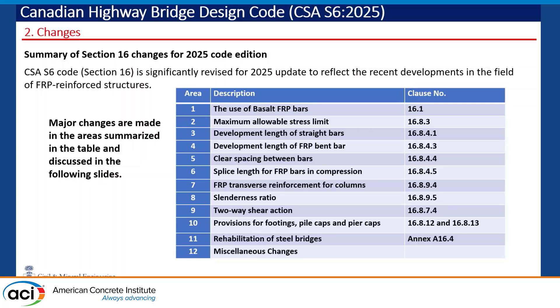One of the things that has come out very loud and clear is that if you use FRP bars as longitudinal reinforcement, your structure is going to be much softer and your capacity is going to be lower. But you can still consider it as a seismically resistant structure, albeit with lower capacities.